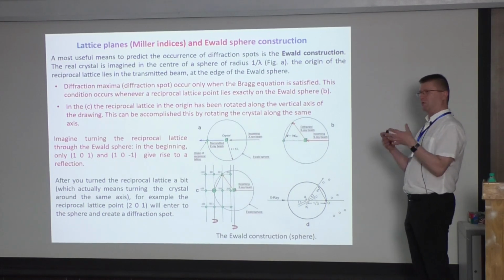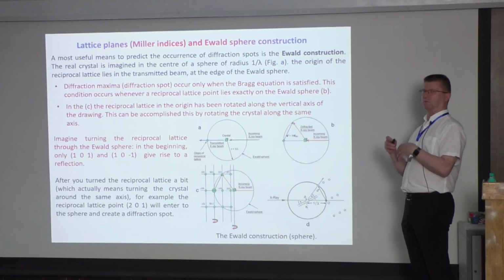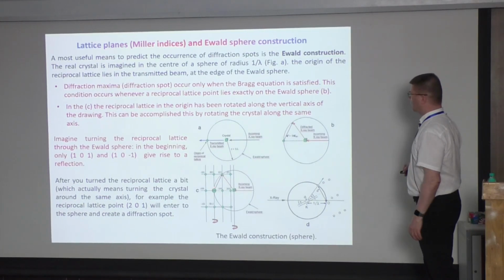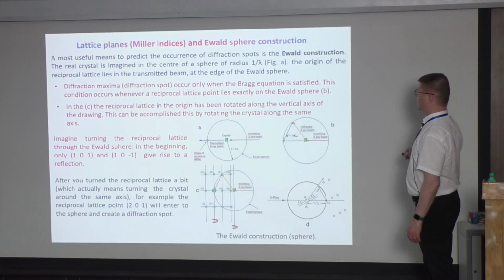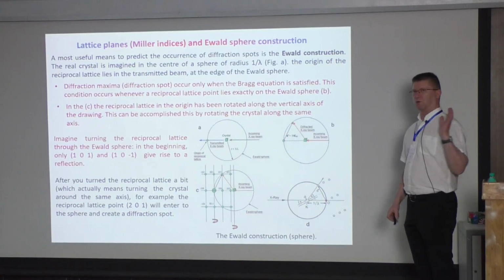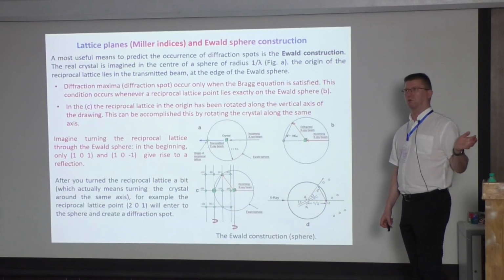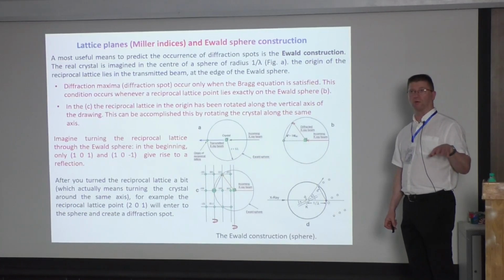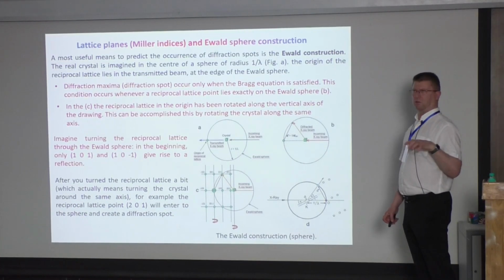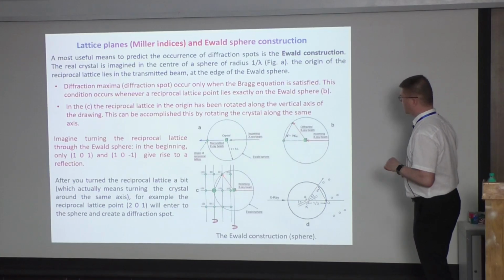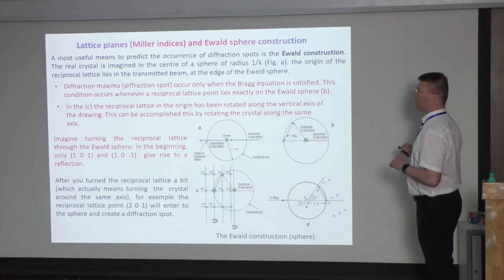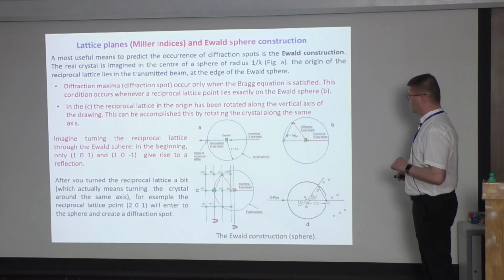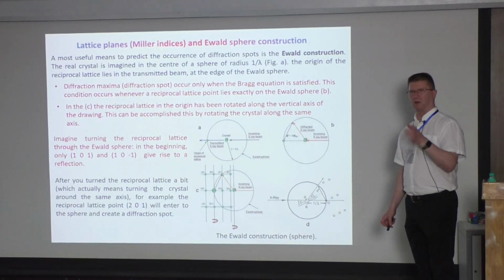But now the point of how the diffraction itself happens, which has been mathematically described, is that you create a sphere around your crystal. It's called the so-called Ewald sphere. Quite probably, if not today, tomorrow I will show you a simulator program which can visualize this. You can calculate around your crystal an Ewald sphere, which has a radius of 1 over lambda, so this sphere depends on the wavelength.